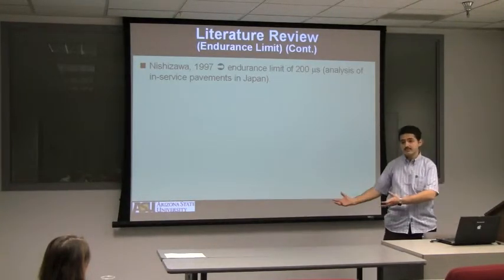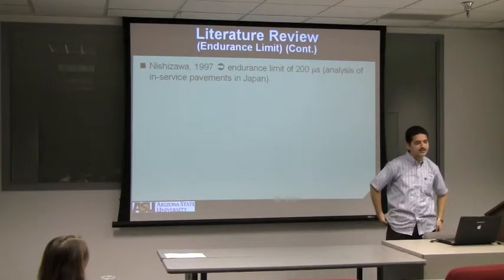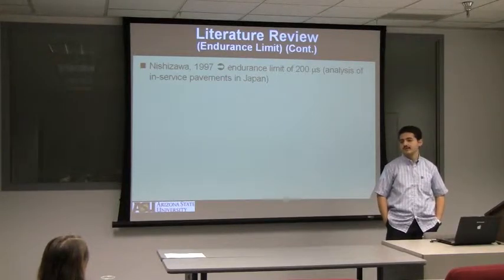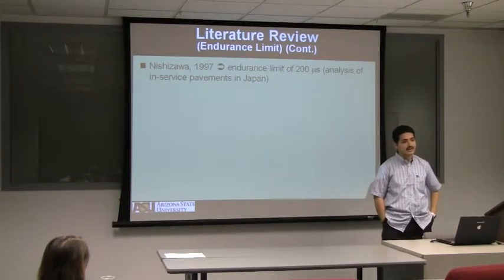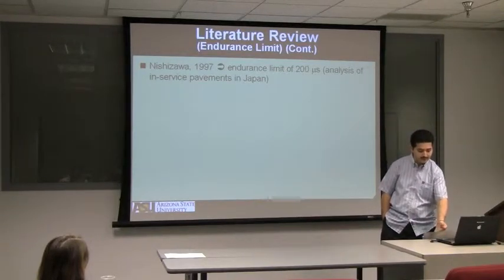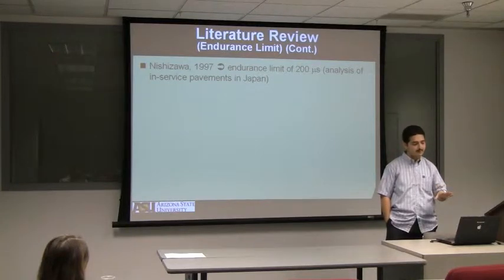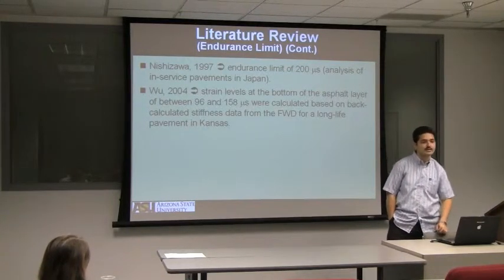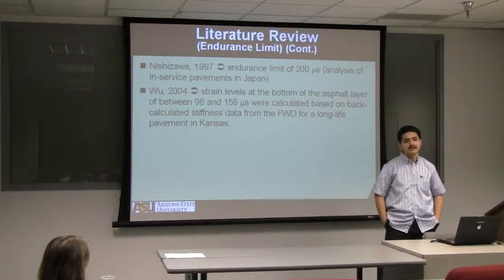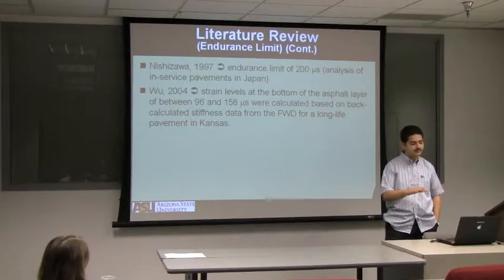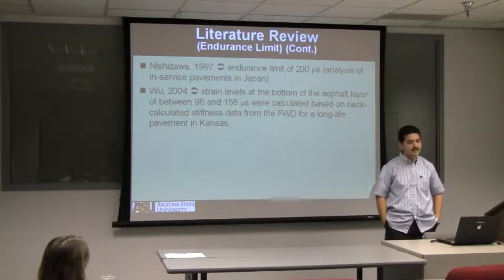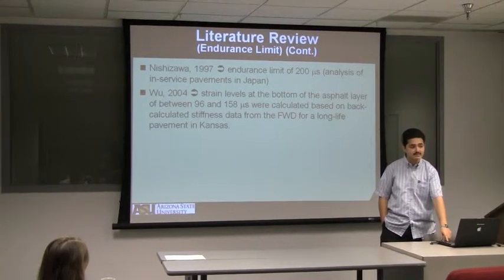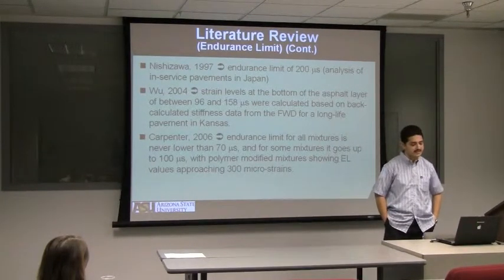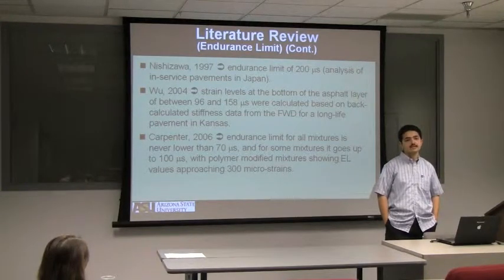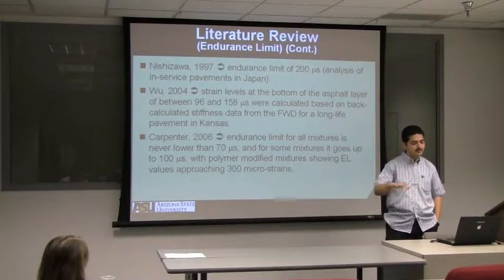Then this concept traveled all over the world and went even to Japan. When Nishizawa in 1997, he also reported that the endurance limit is about 200 microstrains, and he came up with this conclusion based on some analysis for field pavements in Japan. Wu in 2004, he also reported that the strain levels at the bottom of the asphalt layer ranged from 96 to 158 microstrains, and he got that based on back calculation using the falling weight deflectometer in some pavements in Kansas.